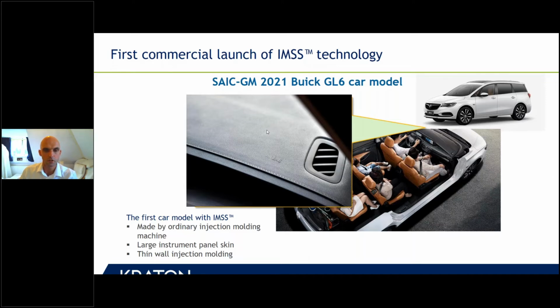Normally, the current standard is PVC slush molding, or in some cases, I think they also use EPDM, but it's mostly PVC. That's something the automotive industry is worried about because they want to get rid of it for recyclability and also for reasons of weight, because PVC is heavier than a TPE compound. So we developed a technology that can produce such skins by ordinary injection molding machine. It's a huge panel. So actually, the art of injection molding is really important here, and it's a very thin wall application. So it's quite unordinary for an injection molding application.